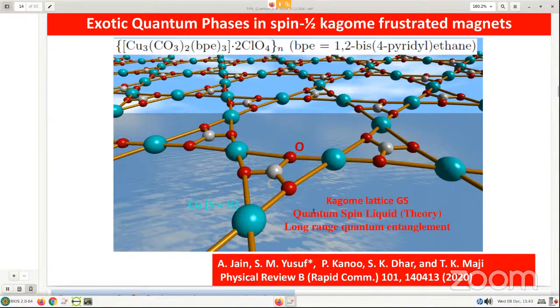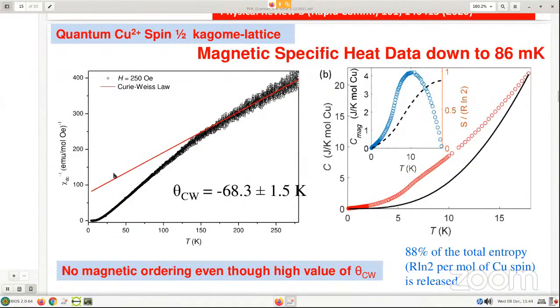So copper involving spin half is what we are talking about. Now what is shown here is the inverse DC susceptibility as a function of temperature, and you see that this theta Curie-Weiss temperature is quite large, minus 68.3 Kelvin. But what we show next is that there is no magnetic phase transition.